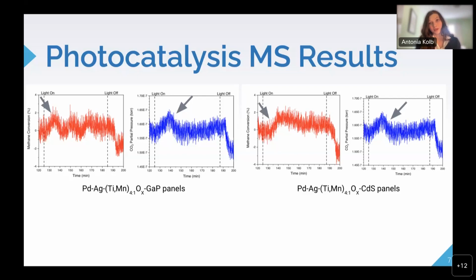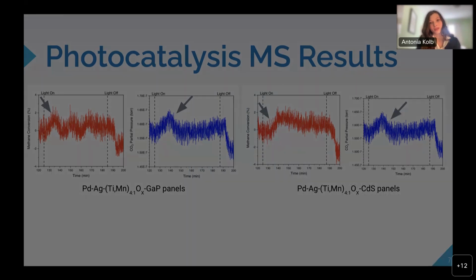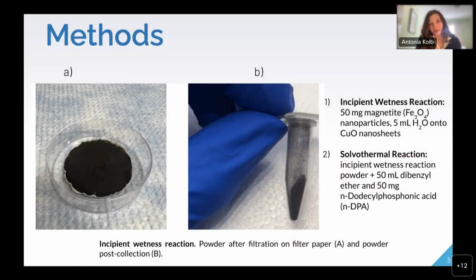Due to the photocatalysis and proof of concept seen in methane conversion, I decided to explore the viable application in oil photodegradation for oil spill removal. I used an incipient wetness reaction to dope and co-functionalize these magnetite nanoparticles onto the copper oxide nanosheets, as seen here. And the two main goals of this experiment were to make the powder paramagnetic and hydrophobic.